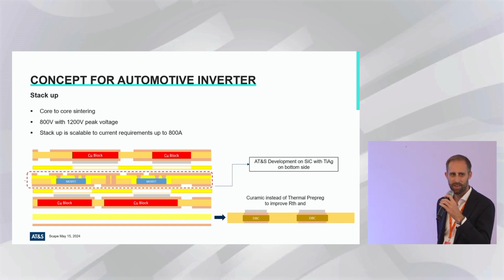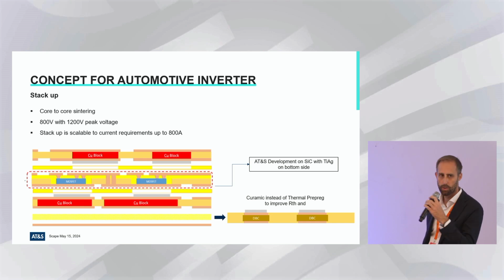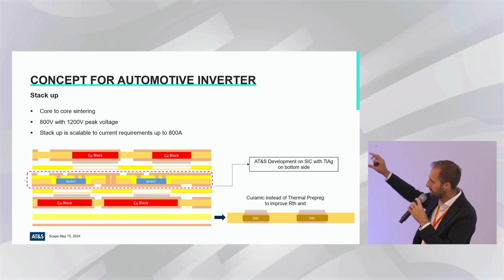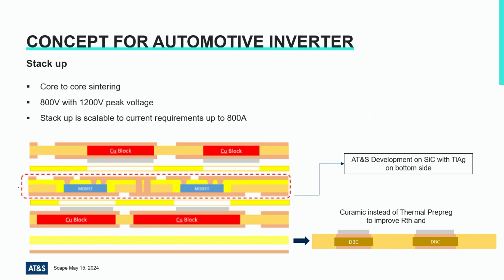What you can see here is a typical stack-up that we are currently using for an automotive inverter. So we have the standard cell in the center where you can integrate the MOSFET in a resin compound. You have a high side and the low side. Then you attach, with sintering, two copper blocks on the top and on the bottom side. Below that, you see either a possibility to go with a thermal prepreg or with a ceramic material. I will talk more about this later in the session. So it's just to give you a teaser of what we can do.